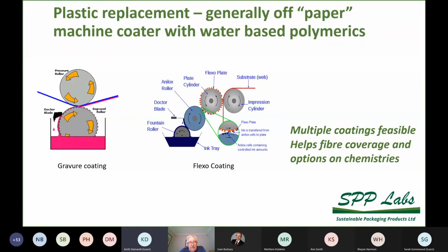So there's two main methods being utilized today, gravure and flexo. So gravure is a fairly simple process. You essentially have an etched roll with cells, picking up the coating and transferring it to the paper substrate. And often you would have several gravure coating heads in line to produce essentially a multi-layer coating. The coating weights that can be achieved with gravure are much lower than rod or blade or curtain, but because you can have multiple heads, you can build up the overall coating weight.